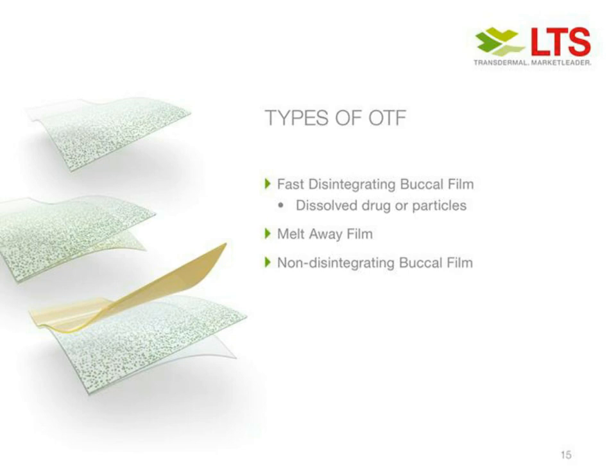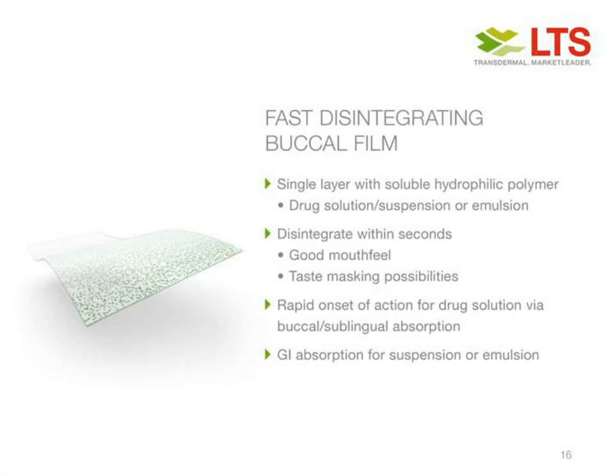So if we go into a little bit more in detail in terms of the fast disintegrating film, typically it is the highly soluble, very soluble hydrophilic polymers where you either have the solution or the suspension, and typically dissolve within seconds, giving a very good mouthfeel, and because of the nature of its rapid solution, you actually potentially get a rapid onset of action via the buccal and the sublingual absorption. For drugs which do not offer the permeability across the transmucosal membrane, of course, will be swallowed. And in that case, then you really offer no additional benefit to the patient. So then that would become a straightforward GI absorption, just like a tablet or capsule.